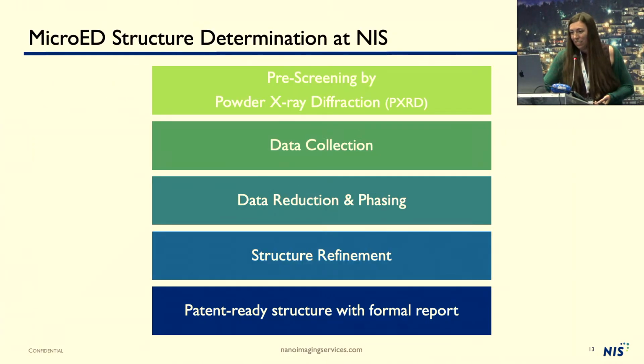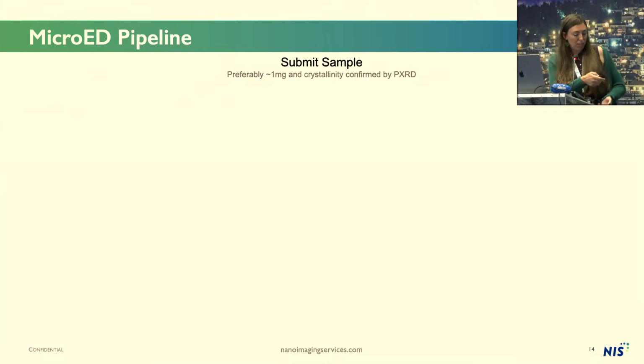All right. So, as I said, at Nanoimaging Services, we routinely determine structures for people working in pharma and other industries, and I'll share a bit about how our pipeline works. We start with sample submission, and generally we ask for about 1 milligram of material. We can certainly work with less, but it's always easier to have a little bit more to work with. We have also been asking that our clients confirm that their sample is crystalline first by doing a quick powder diffraction scan of their bulk material, or they can perform that with us, and we'll just take a small amount of that 1 milligram and collect a spectra just to make sure that the sample's crystalline and we're not wasting microscope time.